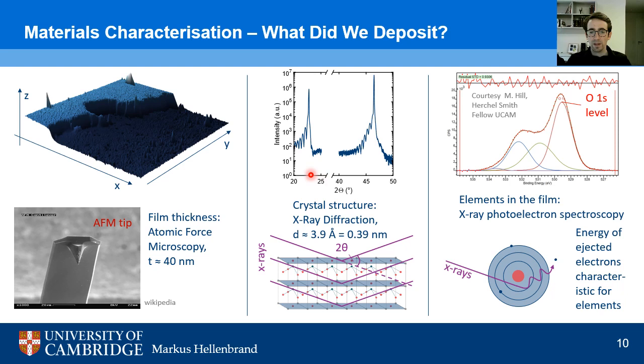So we measure the intensity of the diffracted beam as a function of the angle, and you can see that for some angles there is no diffraction at all, whereas for others we get very high and very sharp peaks. And again, from the location, from the position of these peaks with respect to the angle, we can calculate the distance between the atoms, and thus what kind of crystal we have. So again, in this example, the distance between the atoms was measured to be below a nanometer, and again, we have a very good resolution with this technique.